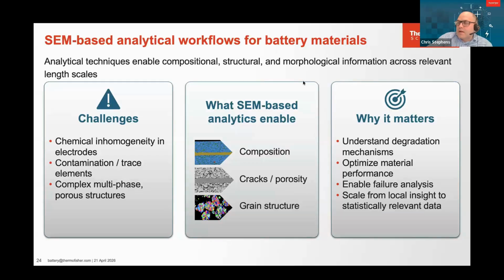So the SEM-based analytical technique addresses this because it's providing spatially resolved information on composition, morphology, porosity, the cracking, and the grain structure, and it's doing this on the relevant length scales. So it means that we can identify the chemical inhomogeneities in the electrodes, we can detect the contamination and the trace elemental segregation, we can quantify the cracks and the pore networks, and we can resolve the microstructural features that might govern the transport or the mechanical stability.